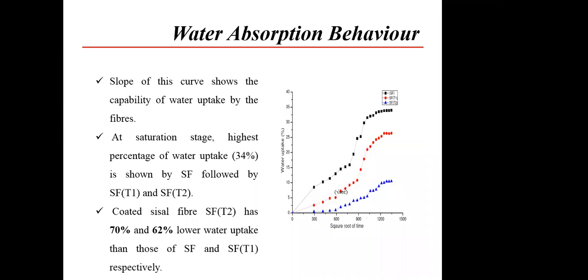Water absorption behavior from the diagram. This graph is plotted between the water uptake percentage and square root of time in seconds. First, the black color shows the untreated sisal fiber, which uptakes more water, but after treatment water absorption by the fiber is reduced.